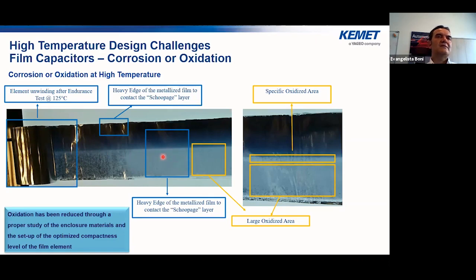It's possible to see that it is a very transparent and much lighter part when the metal is turned to oxide. We can have some general oxidation, or we can also have some specific oxidized areas, as in this small part. So the oxidation has been reduced through a proper study of the enclosure material. We speak about box and resin, but it's also important to optimize the process parameters in order to obtain the right compactness level of the internal film element.